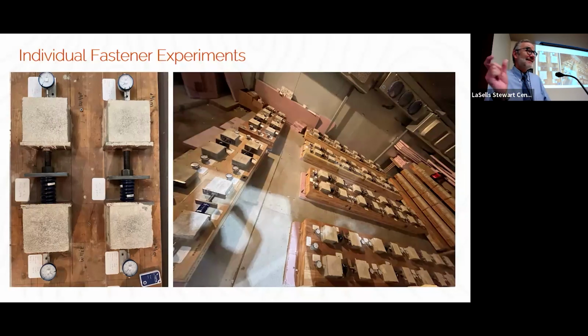Every single spring is individually calibrated so that as they creep with time, we measure the amount of deformation, and we know how many turns of the nut to get the force back up to what it needs to be. The other thing you notice is every single one of these has a manually read dial gauge, rather than relying on electronics, because if you have temperature change, your electronics actually drift as well. So we have purely mechanical measurements.